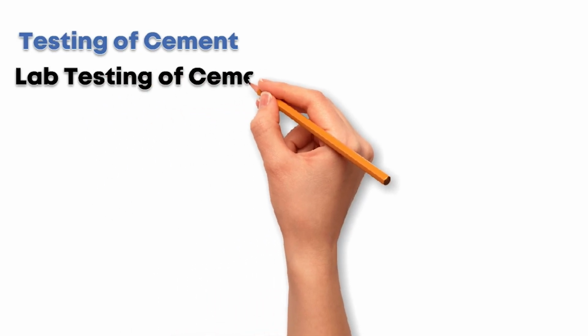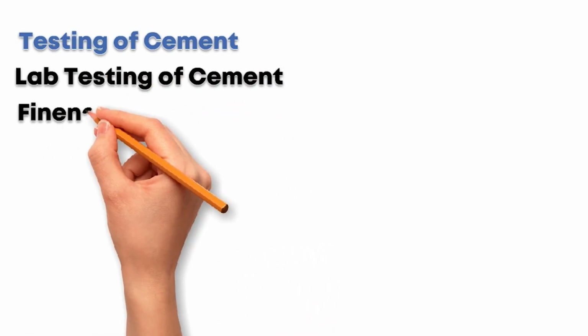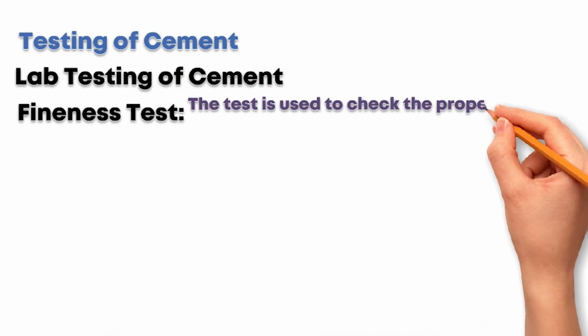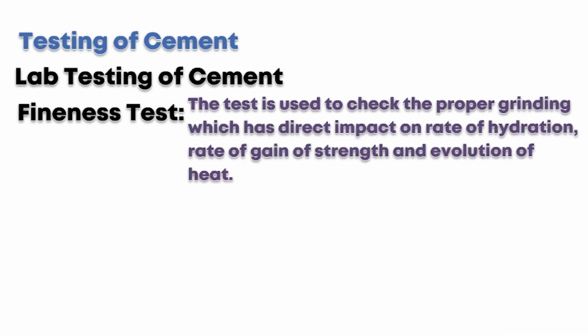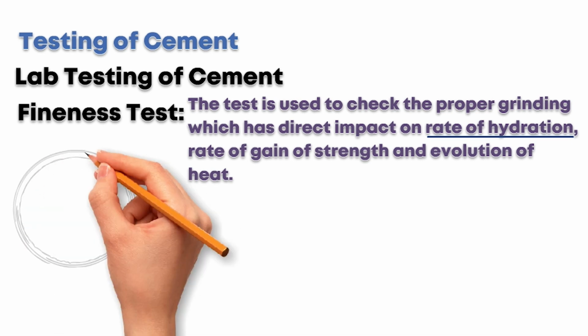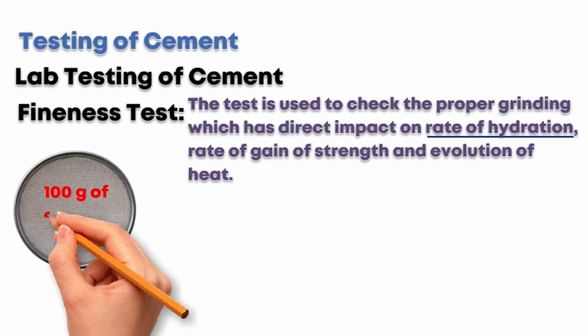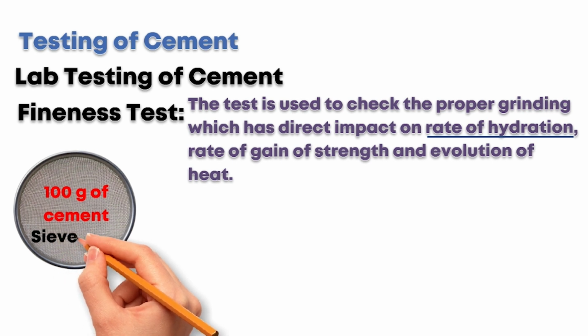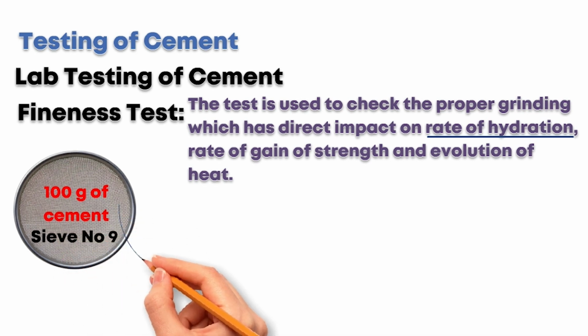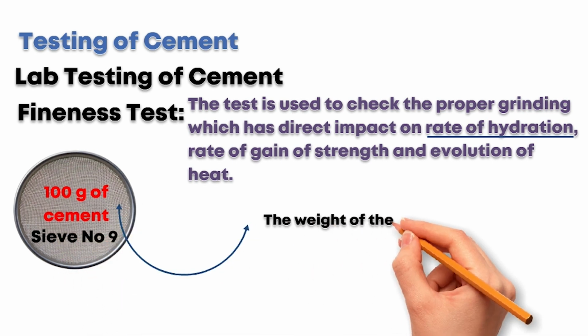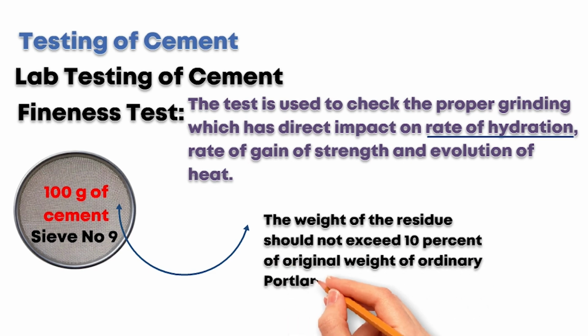Now let's discuss the lab tests of the cement. This includes the fineness test. The test is used to check the proper grinding, which has a direct impact on the rate of hydration, rate of gain of strength, and evolution of heat. Sieve test: take 100 g of cement and place it on sieve 9, perform sieving for 15 minutes. The final results demonstrate that the weight of the residue should not exceed 10% of the original weight of ordinary Portland